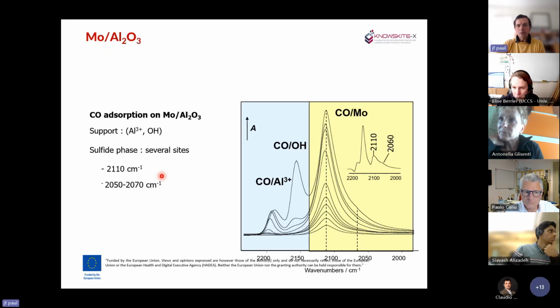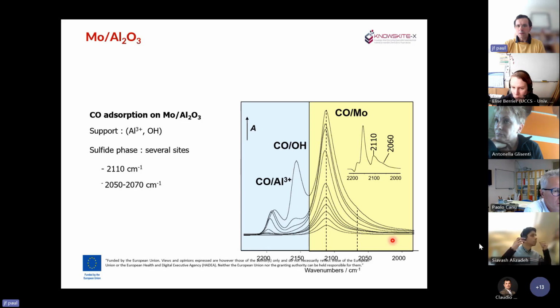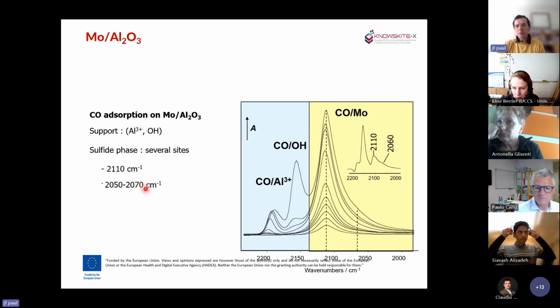So here you have the result for the adsorption of CO. One part is for the adsorption of CO on the alumina on the OH group, so it's not a problem. And here you have the part which corresponds to the adsorption on the molybdenum, and formally you have two bands which are in this area. So 2110 cm^-1 and 2050 cm^-1. One strong one and one smaller one.